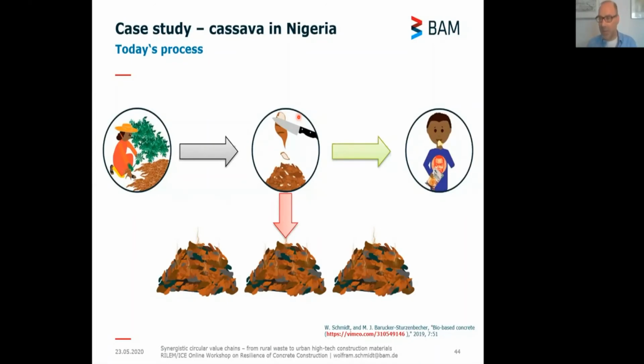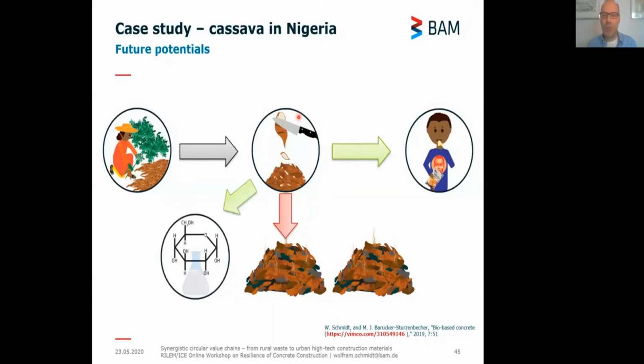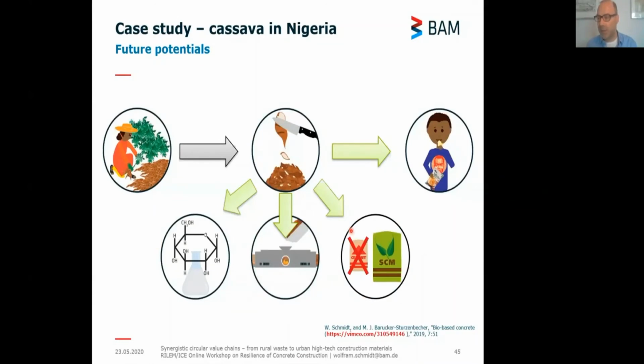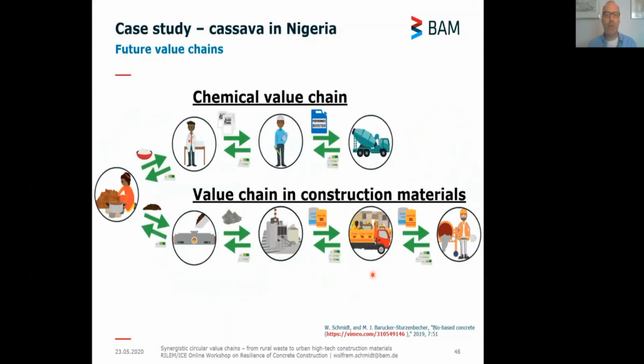But instead of dumping them away and giving them no further value, it would be possible to develop an organic component that helps to reduce the water in concrete. And then it could be used for co-fueling, and eventually the ashes of these cassava peels are reactive, they are pozzolanic, so they can help to replace cement in concrete. So with something which formerly had no further value chain, it's possible, only based on the waste, to produce one value chain in the chemical construction business, and another value chain in the mineral binder business. And these two value chains are not even competing, they are synergistic.